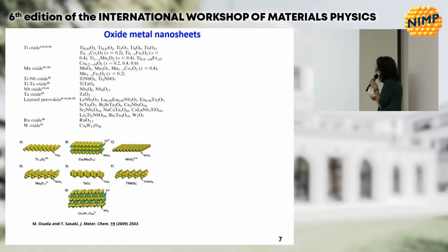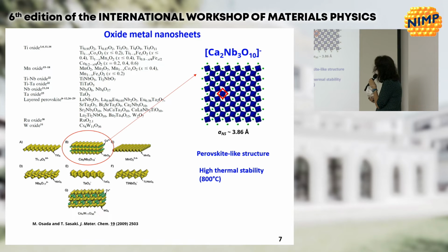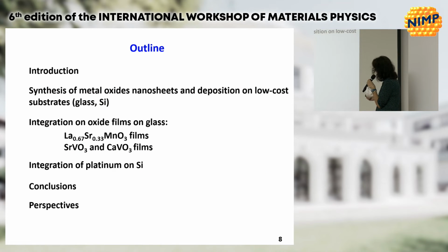So there exist a lot of oxide nanosheets. Most of them are listed here. And today I will talk mostly about this one. This is a calcium niobate nanosheet. You can see here the structure in plan view. It has a perovskite-like structure, as you can see, with a square lattice, which is close to 4 angstroms, as for perovskite. And also, this kind of nanosheet has high thermal stability up to 800, 1000 degrees.